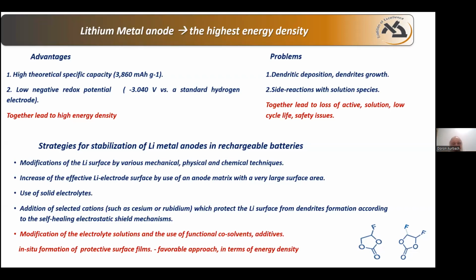But I gave up because I realized that with lithium metal, we have troubles. The major issue is dendrite formation. We have passivation, which is not complete. So the cells become dry. We have inevitable side reactions, and it appears that using lithium metal is very problematic. But then during these two decades, we have development, and there are approaches for how to protect lithium metal.